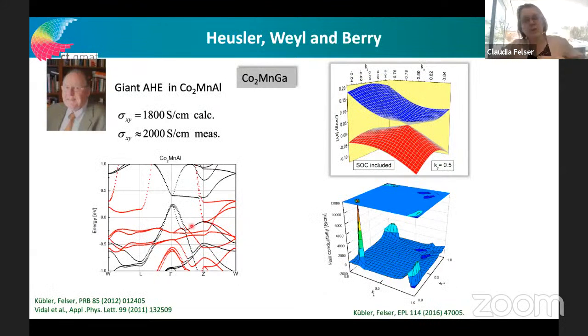And this is already old work, which was done in the context of nice measurements of Gerhard Jakob's group at this time in thin films. They found out that Co2MnAl has a giant anomalous Hall effect. And at this time, it was a big question mark, why? So together with Jürgen, we worked with DFT on this, and we did Berry curvature calculation and calculated the anomalous Hall effect. And here you see this nice crossing point in Co2MnAl, which is isoelectronic to the gallium compound. Later we published the gallium compound also. And you see that there's a very nice agreement with the measured and the calculated anomalous Hall effect, which was published at this time without really understanding.